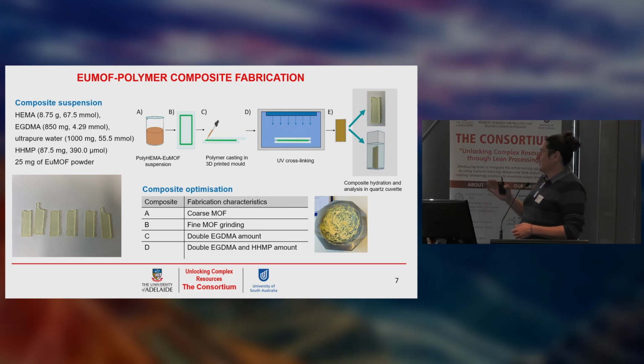So the next step in the process is to incorporate the MOF, and that's the sensing component, remember, inside a polymer matrix. The polymer matrix helps to disperse the MOF, provides a large surface area for the MOF to interact with ions in solution, and prevents degradation of the MOF. So this is done by taking a solution of the MOF in a monomer and then polymerizing the monomer around the MOF to embed the MOF within a polymer matrix. So it's a relatively simple process.